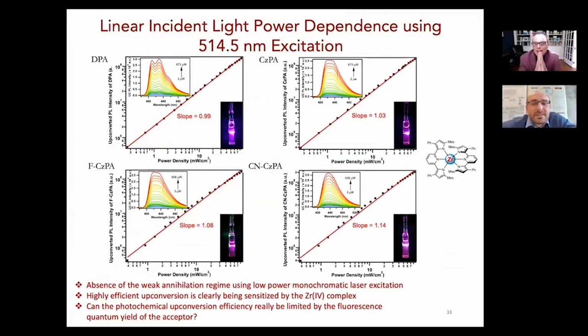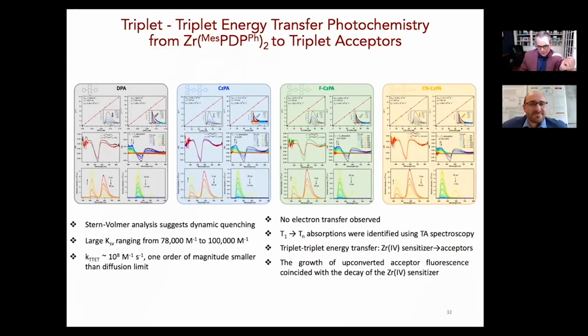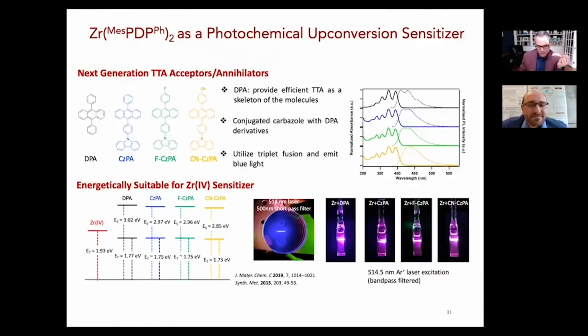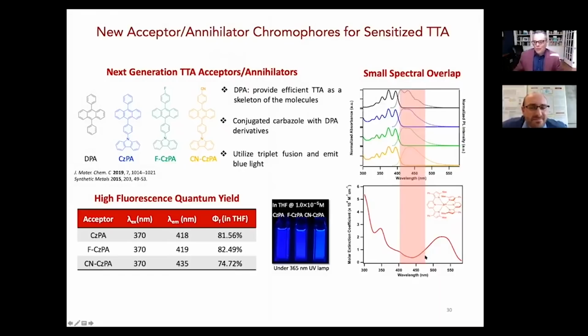This is always the challenge. Ideally, we would love the zirconium photosensitizer to absorb in the near infrared, but it just doesn't. Let me go to the spectra, I think they always really tell you everything that you need. Basically, we recognized immediately that this is a good surrogate for the Q band of a lot of the porphyrins that we've used in the past. And as the first proof of principle, we just said, we should just do yellow and green to blue upconversion. The reason we said blue would be good is the fact that the absorption band here hits a minimum and we would avoid a lot of the inner filter effects.